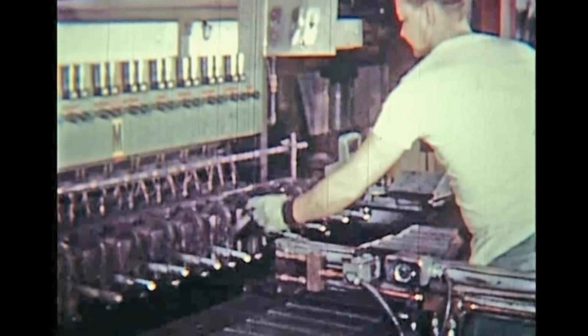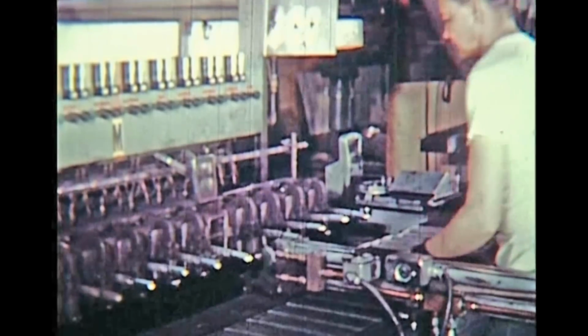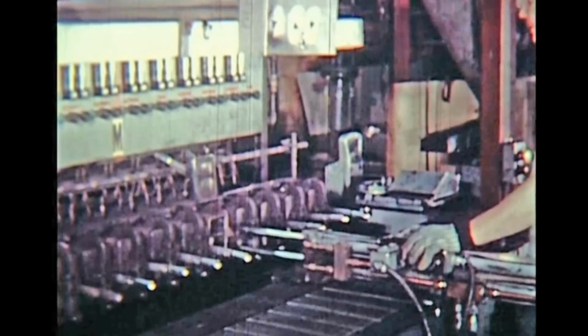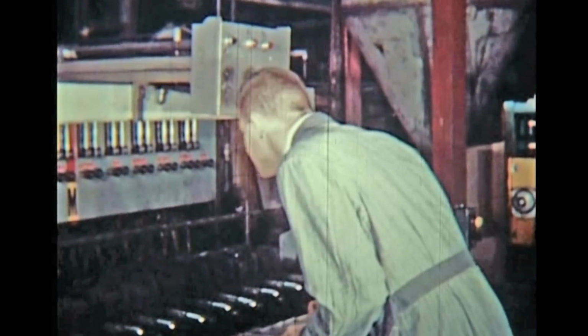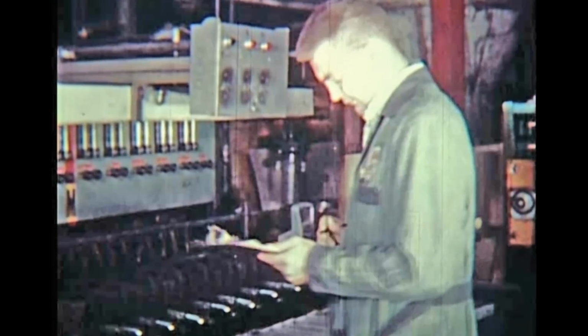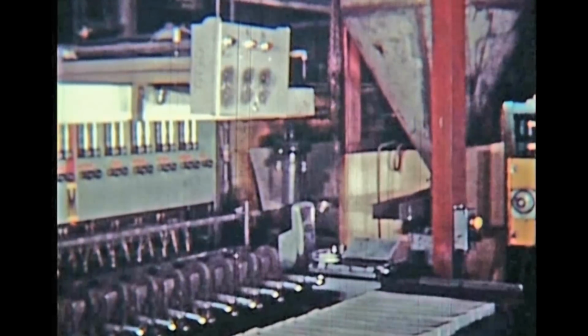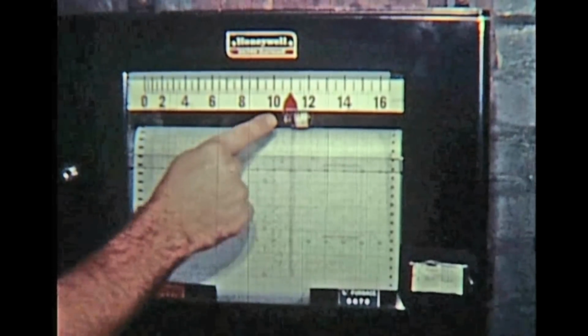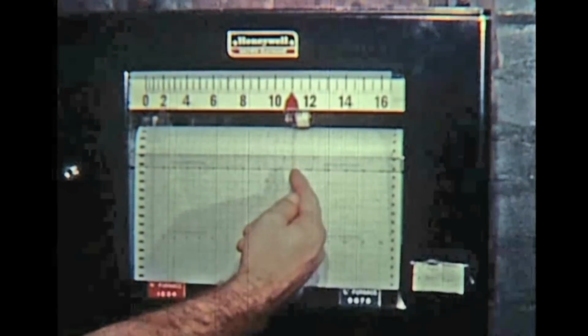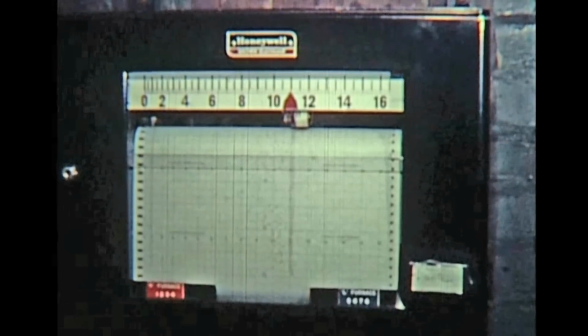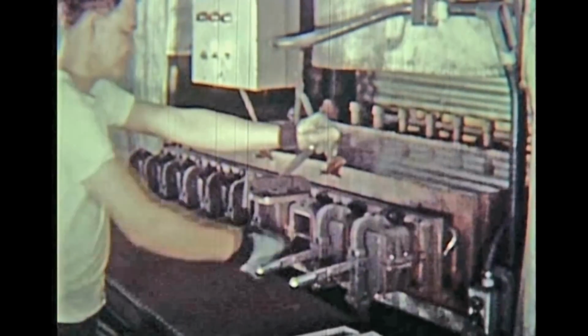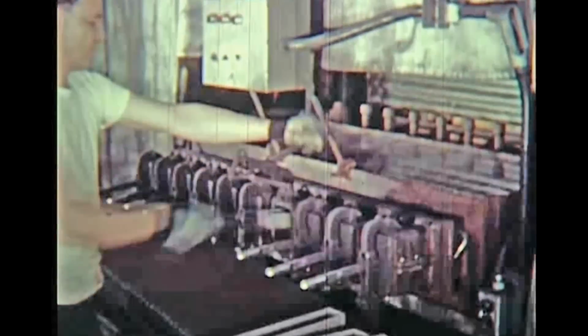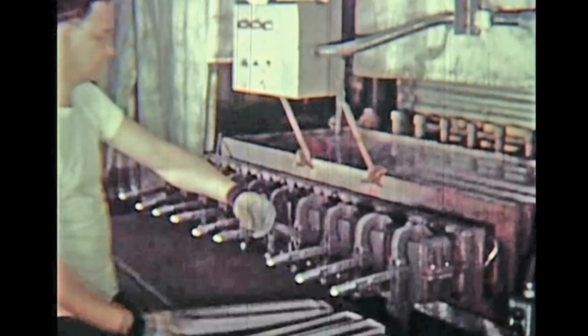When the boats are filled, they are stoked or pushed into a dual tube furnace for final reduction. The operation requires precise controls on boatload quantity, stoking time, hydrogen flow, and temperature to ensure the removal of the proper amount of oxygen from the oxide. Purity, specific particle size, and distribution are other vital factors affecting the quality of the finished product. Boats are removed from the furnace every 18 minutes.